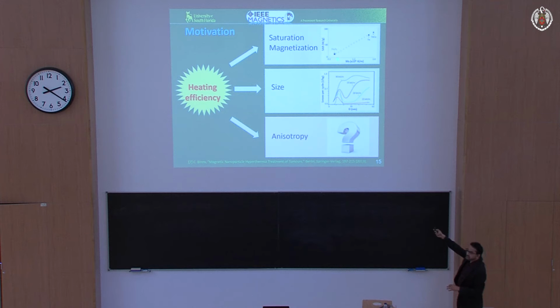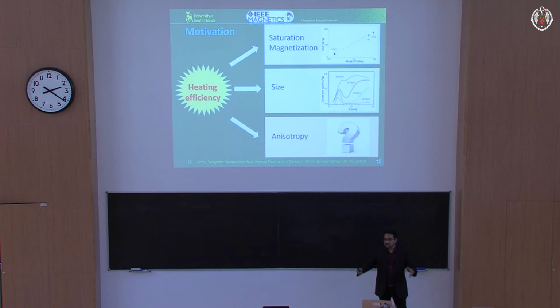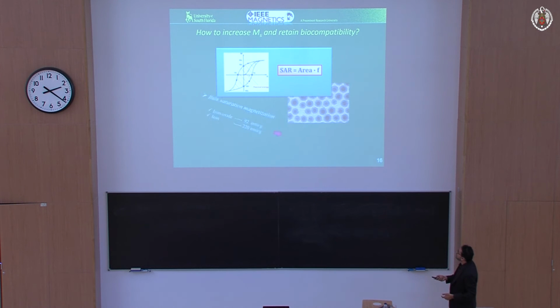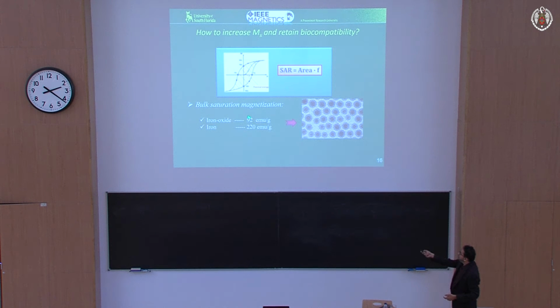But we took a look at this. Can we fool the cells? All we need is a biocompatible surface, right? So can we make a core shell particle with iron, which has a larger saturation magnetization, completely encapsulated by iron oxide using a core shell approach? That's what we wanted to try first. I'm going to show you some results. Keep in mind that we want to make core shell nanoparticles. If you look at the bulk saturation magnetization, iron oxide is 90, iron is much bigger. So if you can make a core shell but keep the surface biocompatible by having magnetite outside and iron inside, the chances of getting a larger effective saturation magnetization and higher SAR is possible.